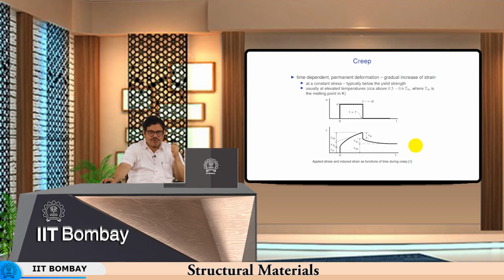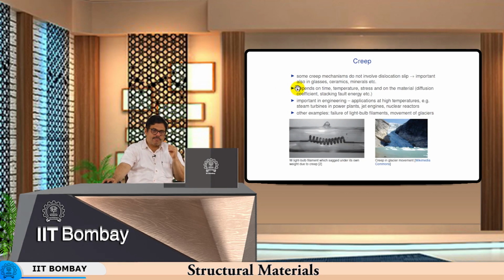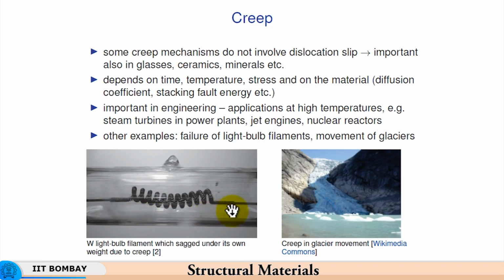So, the life of the component can often be curtailed, not because it has yielded, but because it has acquired a certain creep strain after functioning for a prolonged period of time under high temperature and high stress. Now, some creep mechanisms, as has been said, do not involve dislocation slip, and one of the classic examples of creep is the creep of the heating element in an incandescent lamp, where over a period of time it gets heated up and then sags progressively due to creep, under its own weight. Therefore, after a certain duration of service at the service temperature, it will finally sag beyond limits, meaning it will break.